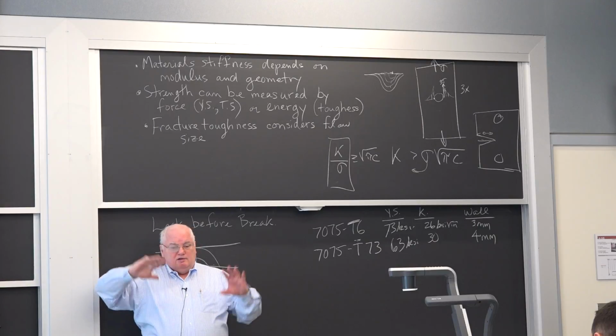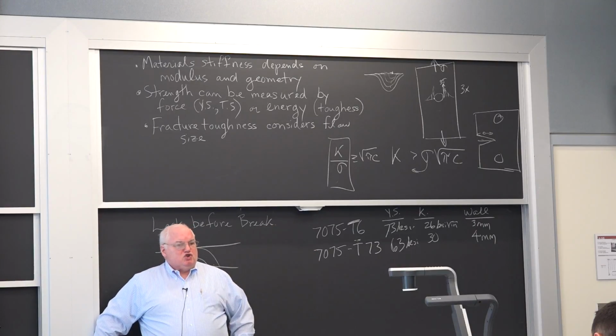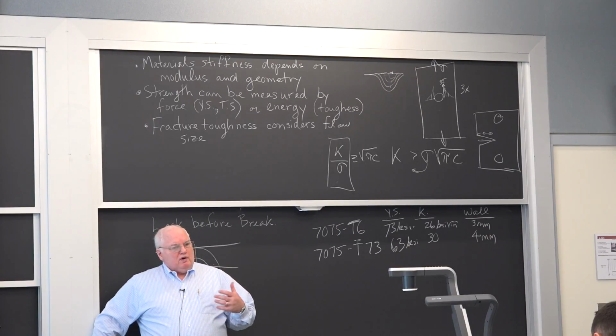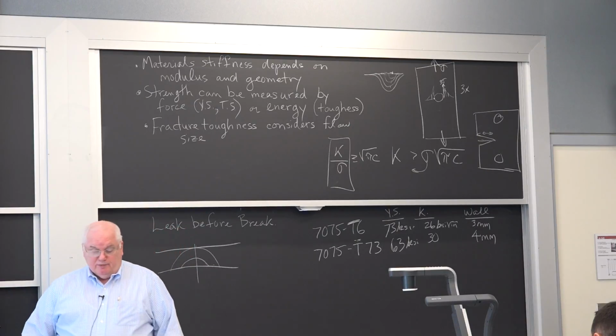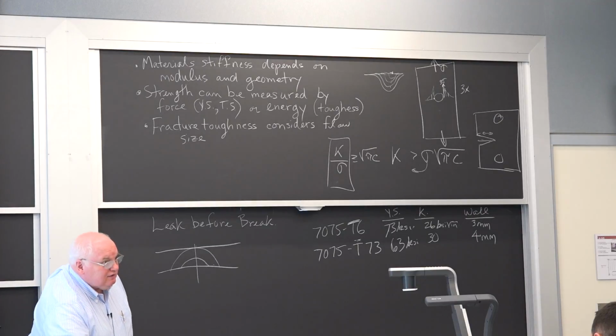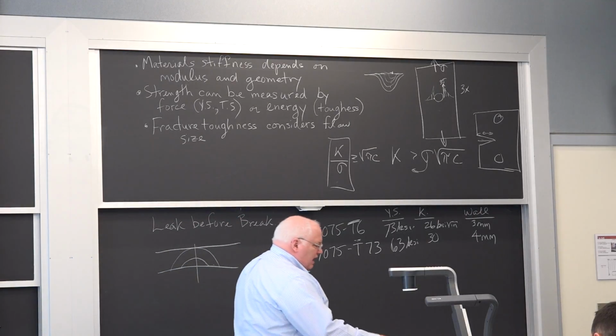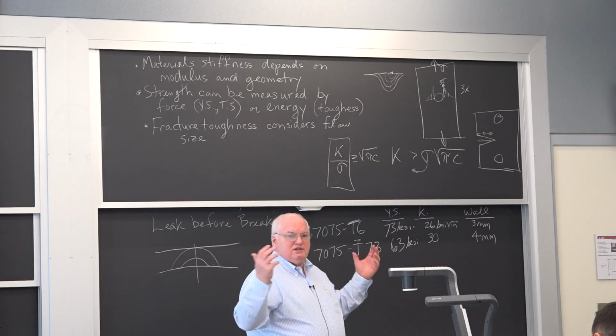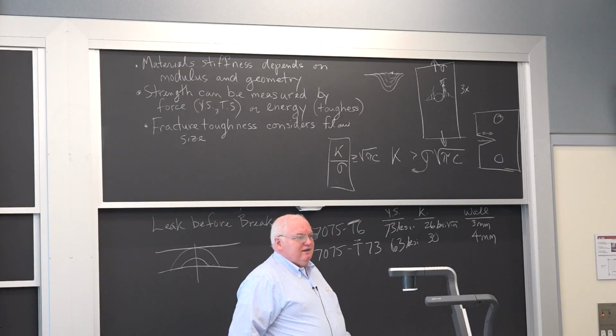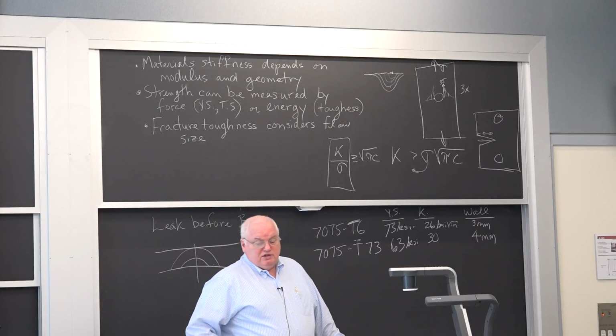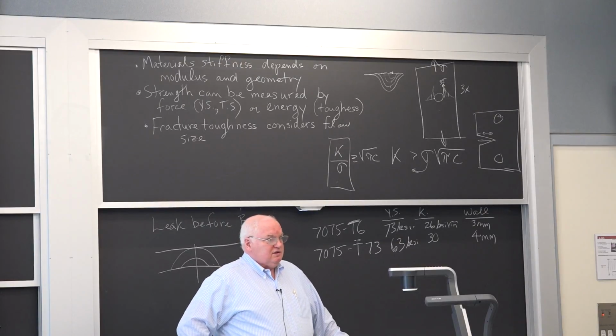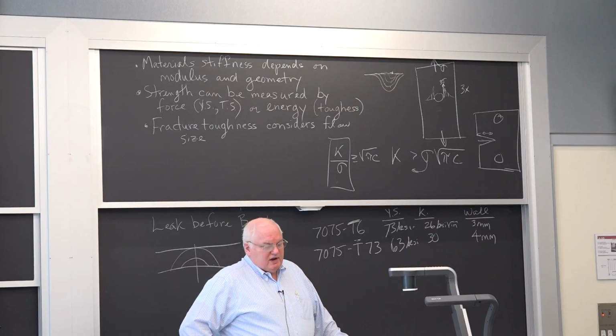Okay? Today, we got aluminum alloys. We can make them super strong, and we make them into bats, which are very thin wall, and they typically will crack, and they won't work very well as a bat, but they don't shatter in someone's hands, but they cost you another $300 to buy a new bat. And the bat companies think that's fantastic, okay? They could make these things that would last for 1 or 2 hits, but people would really get upset if it failed after 1 or 2 hits. But it doesn't matter. They still make them, so it only takes 100 to 150 hits before you'll start developing cracks and have to buy a new bat. And they think that's fantastic, okay?